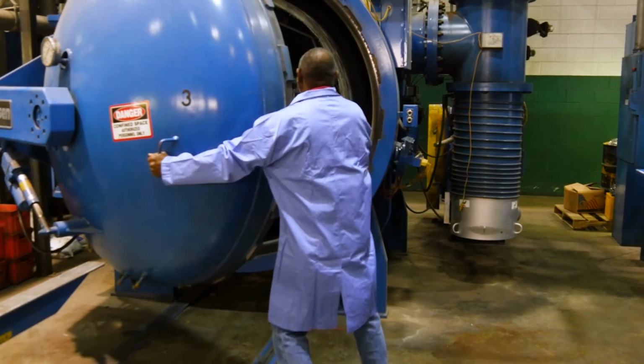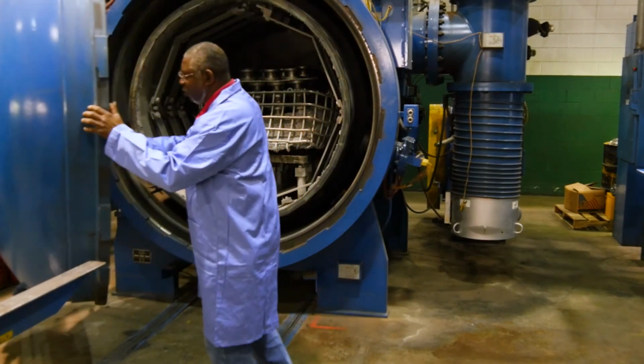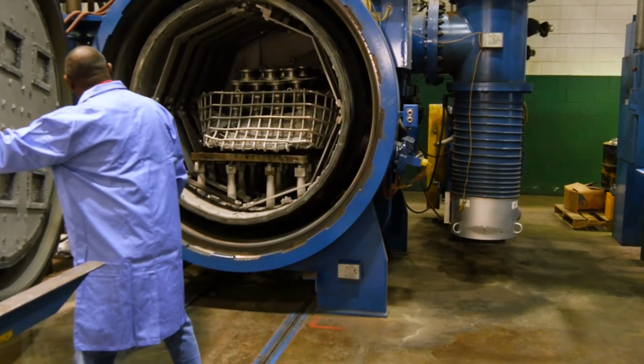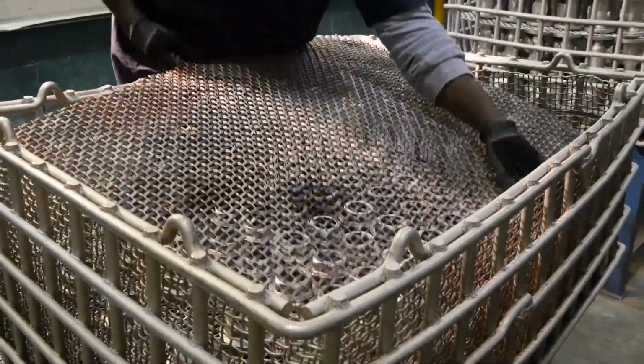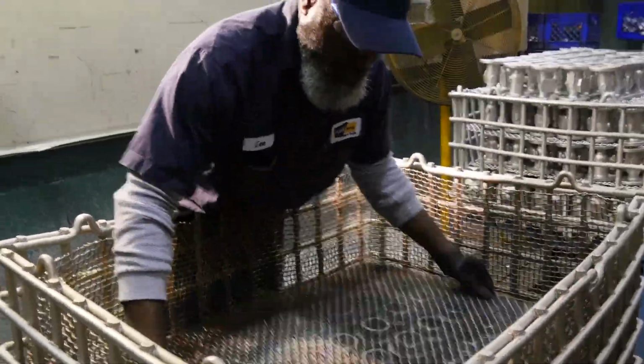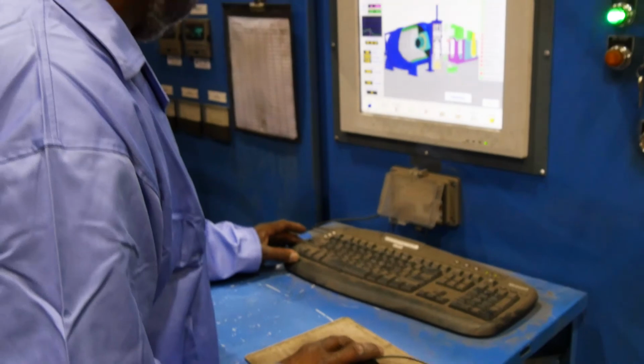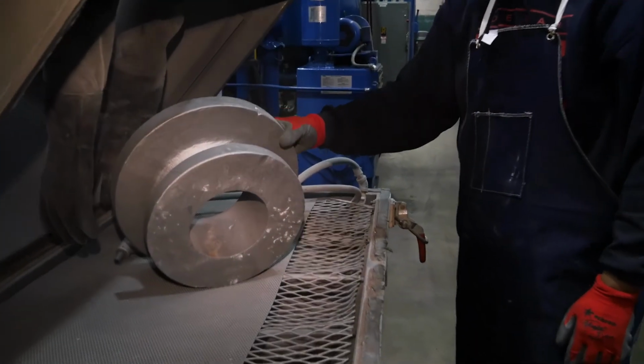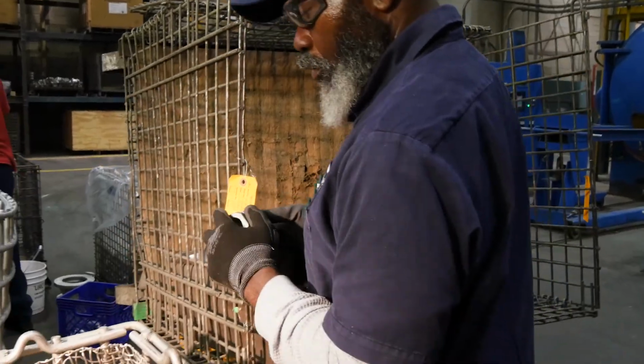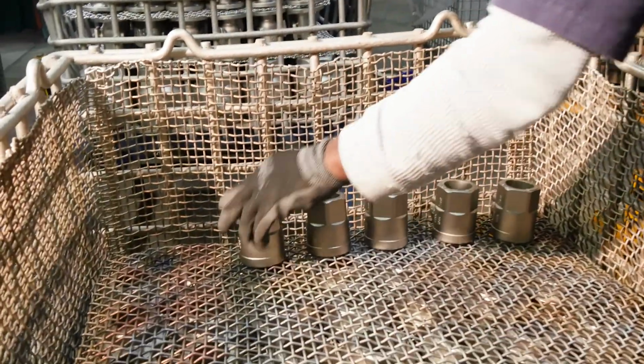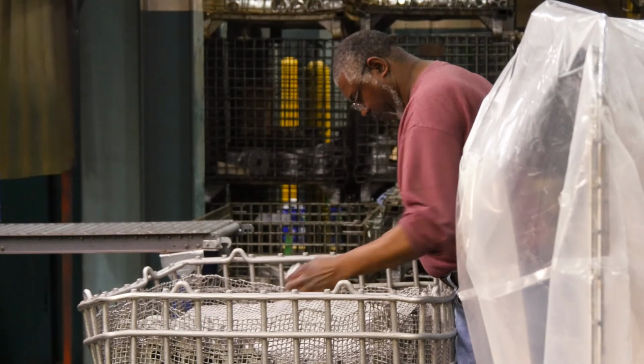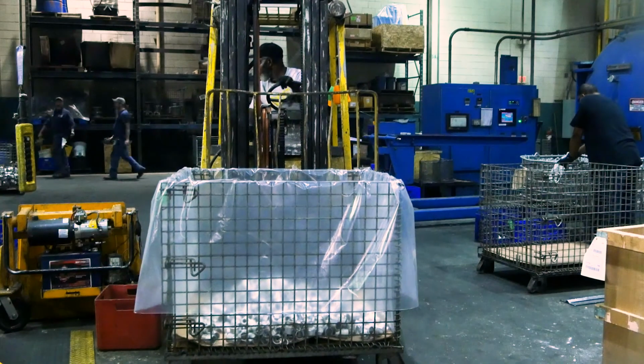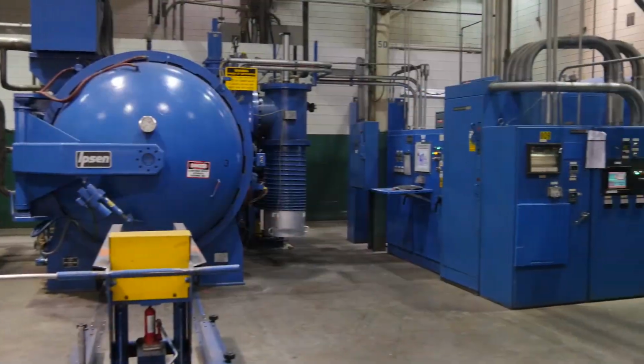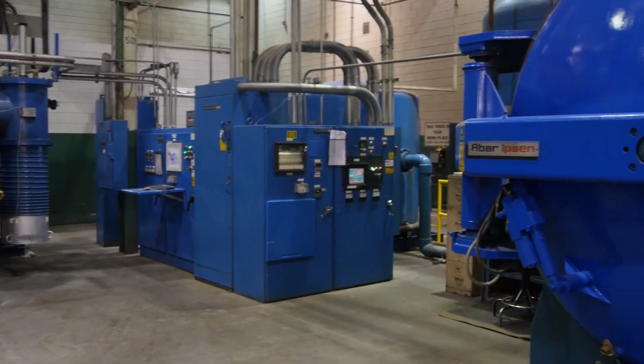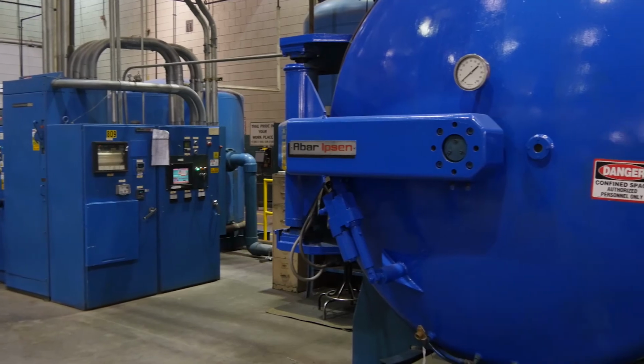Apollo Valves utilizes specially designed vacuum furnaces to ensure pinpoint thermal accuracy and eliminate surface scaling during the entirety of the heat treatment cycle. This heat treatment procedure is critical in ensuring that the corrosion resistance and mechanical properties produced are consistent and highly repeatable. The castings are high-temperature solution annealed and quenched to lock in the desired microstructure that prevents segregation-induced corrosion sensitization.